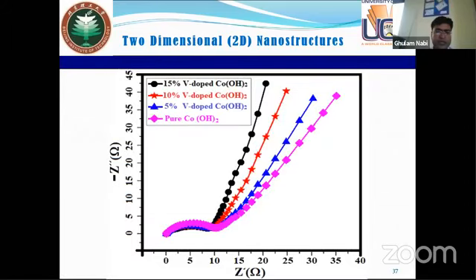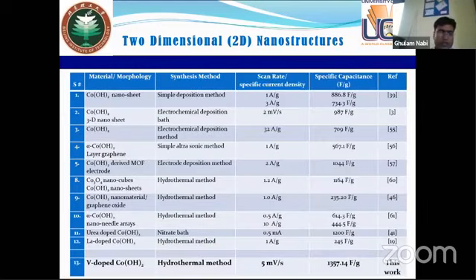Here is the Nyquist graph, or impedance. From the impedance, we can also see that the 15% vanadium doped cobalt hydroxide has less resistance, which is useful for supercapacitors. Along with this, here is the comparison of the vanadium doped cobalt hydroxide with the other materials, which is almost 2 times greater than that of the other prepared materials.